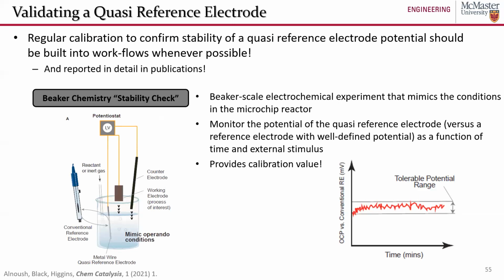One way to calibrate and test your quasi-reference electrode is to set up some beaker-scale electrochemical measurements that mimic the conditions of your microchip reactor. For example, use the same electrolyte that you're using in your microchip reactor in a beaker, use the same working electrode, the same counter electrode, and a wire of the metal that is your quasi-reference electrode for your in situ measurements, and just run your experiments and see if the potential of that reference electrode drifts over time. If it doesn't, then you're in good shape. You can say, okay, looks like our reference electrode is stable, but definitely take into account that there are geometric differences between the reference electrode in your beaker-scale electrochemistry and that of the microchip reactor.